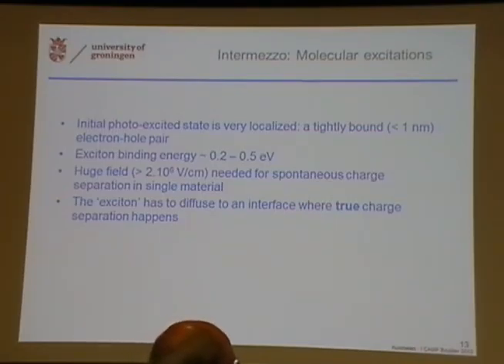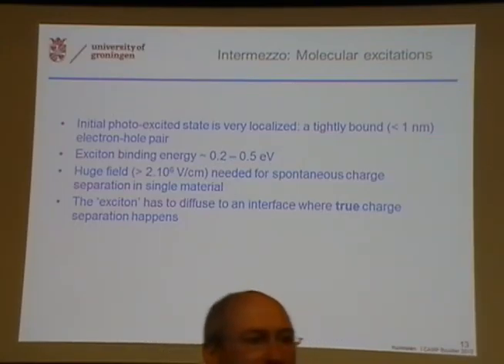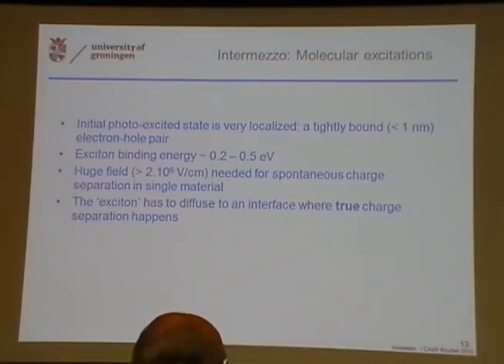That is just not possible because you would simply burn your solar cell, basically. They have a spark and that's the end of the solar cell. So the exciton has to diffuse to an interface where the true charge separation takes place.